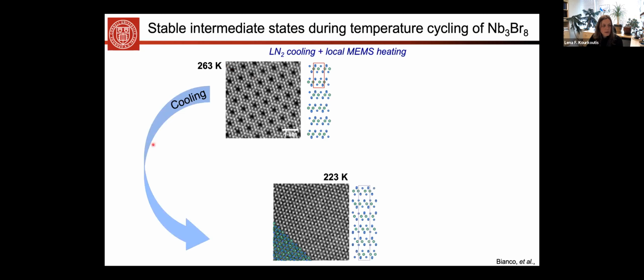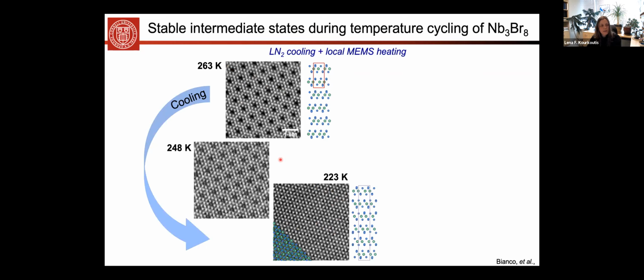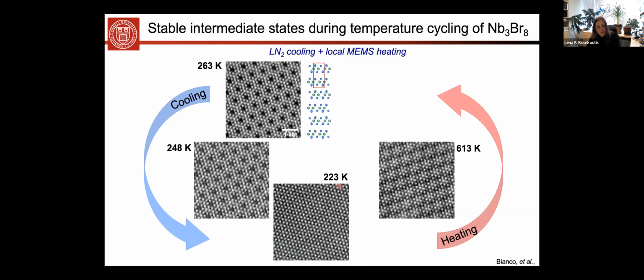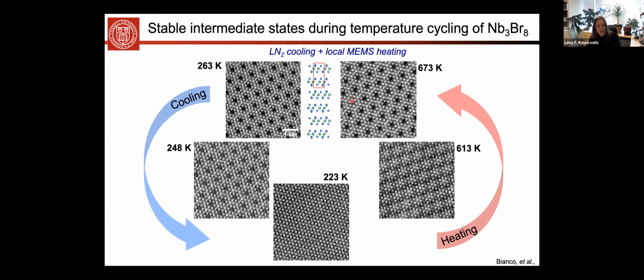When you cool the material down, we are now sitting at 223 Kelvin in the same experiment. You see that you have a very distinct structural transition, and that is reflective of a change to a 6-unit cell repeat compared to the 2-unit cell repeat at the high temperature phase. So yes, we can cool into the low temperature phase and resolve the structure. Now, what's more important, we can do this at intermediate temperature and continuously. And what we actually see, I'm only showing one state, is that you have intermediate phases that are stable as you cool or heat. So here you see another phase that is very different than all other phases that we have observed. And then as you continuously heat, you then recover again the high temperature phase.